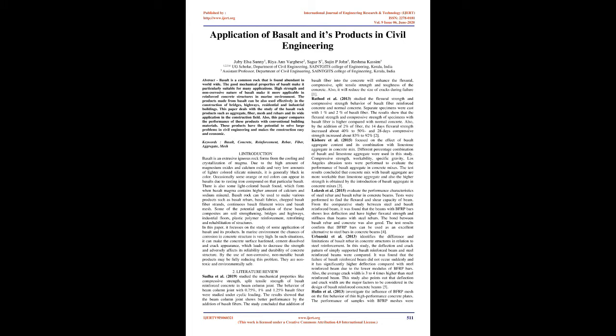2. Literature review. Sujin et al., 2019, studied the mechanical properties like compressive strength and split tensile strength of basalt reinforced concrete in beam column joints. The behavior of beam column joints with 0.75%, 1%, and 1.25% basalt fiber was studied under cyclic loading. The results showed that the beam column joint shows better performance with the addition of basalt fibers. The study concluded that addition of basalt fiber into the concrete will enhance the flexural, compressive, split tensile strength and toughness of the concrete. Also, it will reduce the size of cracks during failure.